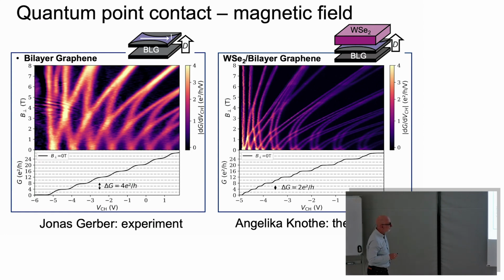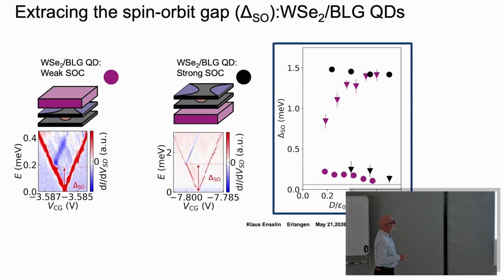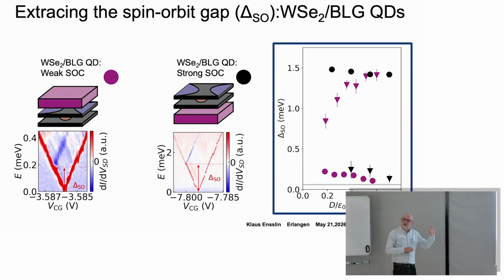Okay, so you can now build a quantum dot. I showed you a TMD. You can build a quantum dot as I've shown you before. You take this quantum dot, that's the part of a Coulomb diamond. You can measure the excited state, and you can measure for weak and for strong spin-orbit interaction. And you see here, you can directly read off how far this goes. It's 0.2 milli-electron volts, and here it is 1.5 milli-electron volts.